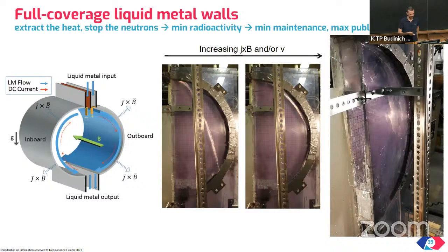Regarding the question about the HTS being damaged by radiation, by neutrons, by heat, and not only the HTS, by the way, the vessel itself, we protect both the HTS and the vessel by means of liquid metal walls. These are walls of lithium-lithium hydride, as shown in the next slide. The MHD, the simple physics that allows us to have it stick to the wall, is that the liquid metal is injected from the top and is forced to flow along the surface by means of J cross B forces pushing radially outwards.